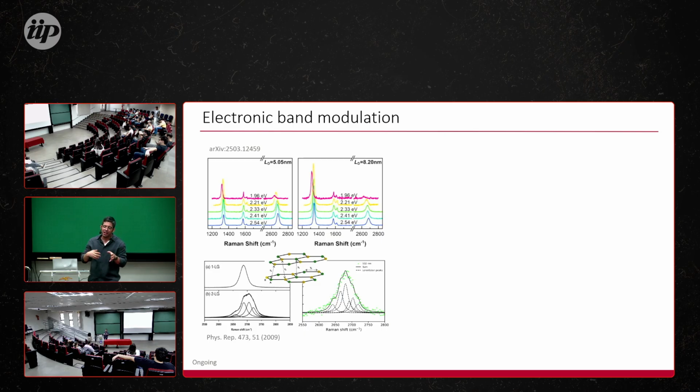I did this kind of measurement for CVD a few years ago, and it's not so easy to figure out everything that's happening, because it's a little bit of a mess. So we still need to improve this kind of synthesis to try to observe. But in that sense, it's just doping. It will shift the peak's position, and if there is incorporation, we will see some defect-related states. That's basically it.